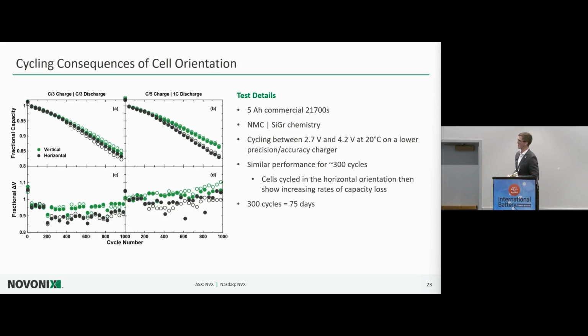So this is just cycling data that was taken on anywhere for 1,000 cycles. So what we did is we had some cells cycling at C over 3 charge, C over 3 discharge, in a vertical and horizontal orientation. And there was a little bit of a difference, but not too much. But it really took hundreds of cycles to start happening. And then we also took some cells and did a C over 5 charge, a little slower, but the discharge was a lot faster in 1C.